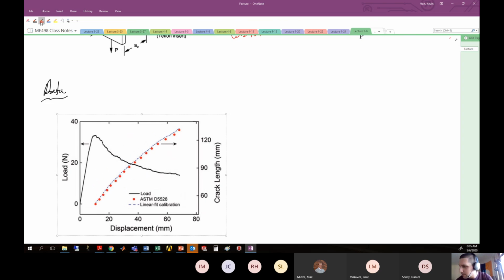All right, we're in black here. We have the load displacement curve. So we're loading, loading, loading, loading. And then at some point, we're getting to a point where the crack is now going to propagate. So we're pulling, pulling, pulling, pulling. And then all of a sudden, we get some crack advance starting to happen.